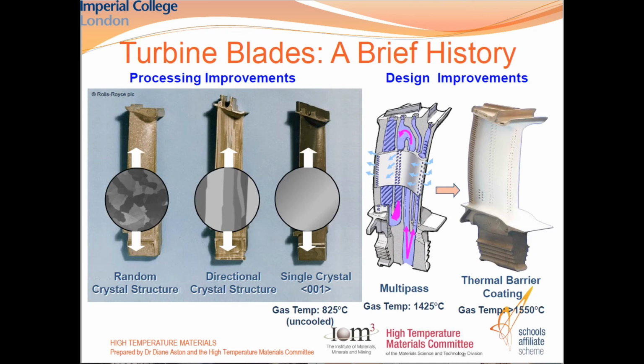Then people figured out how to make these a single crystal, like one grain. The entire thing is one grain, removing the grain boundaries, removing the weak points. And this change alone was sufficient to improve the operating temperature of the blades up to 800 degrees. That's great, but it's half of what we need now. So through design improvements, once we reached the material's capability, the design came to the rescue, and cooling channels were built on the inside of each blade, and that's how they're cooled right now.